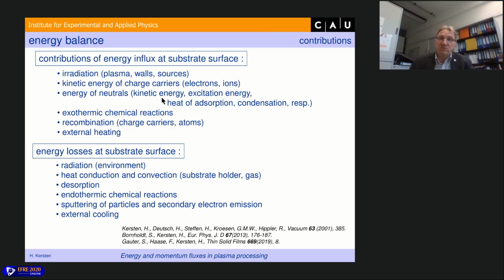There might be kinetic energy of neutrals. For instance, in sputtering, the sputtered neutrals carry a certain energy from the collision cascade in sputtering, and this kinetic energy can be transferred to the substrate, to the growing film. There might be heat of adsorption and condensation during the growing film. There might be exothermic chemical reactions at the surface, which heat the substrate. And there might be, of course, recombination of charge carriers and of atoms, here neutralization and here molecule formation. Then energy is released, and this energy heats your surface, your substrate. And of course, there can be external heating. If you have a heater by infrared or by an electro-ohmic heater, for instance, you can heat your substrate.